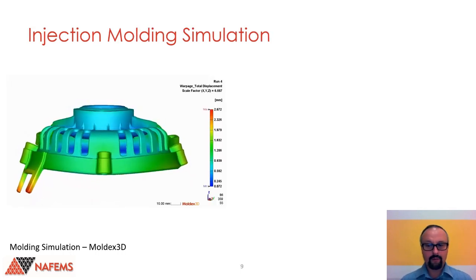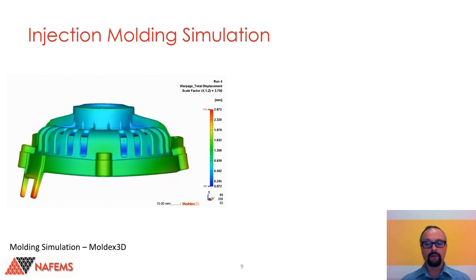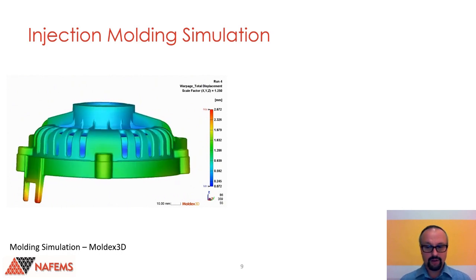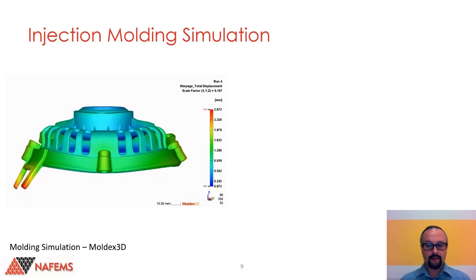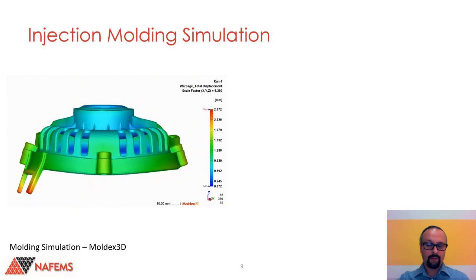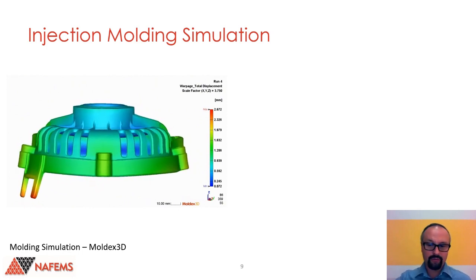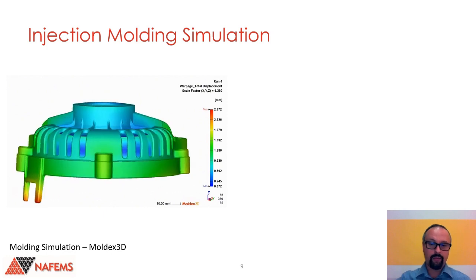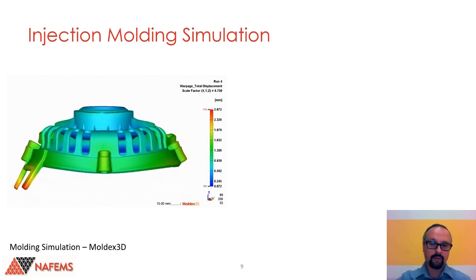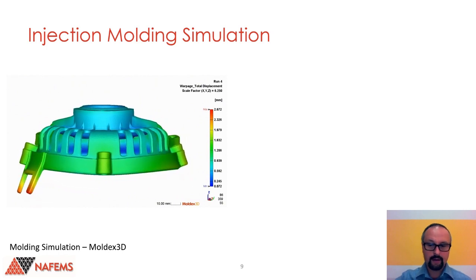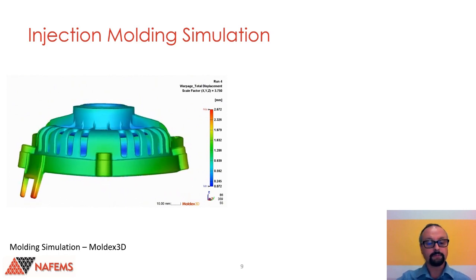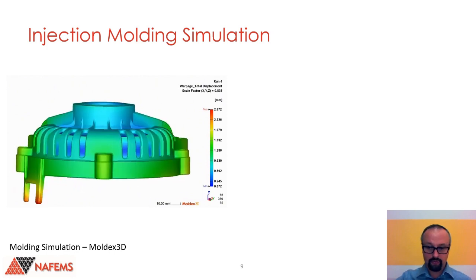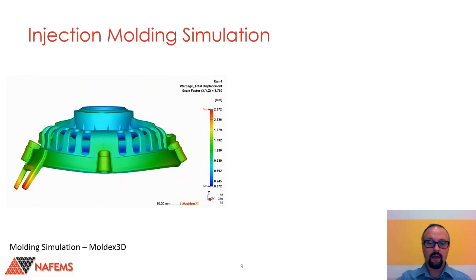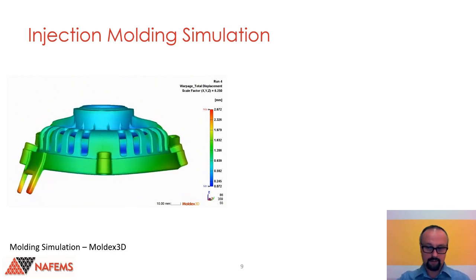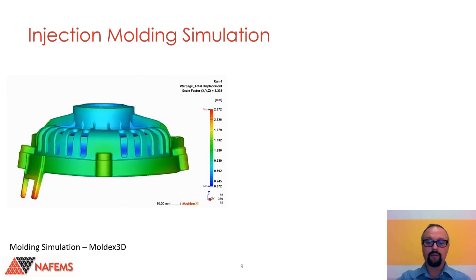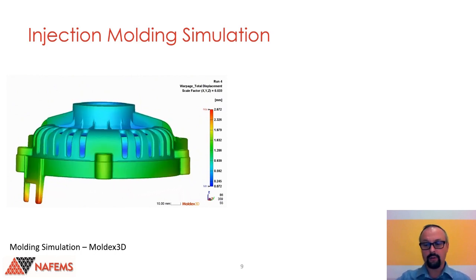Even though we design our geometry according to these DFM rules, with a constant wall thickness, we still need to double check it with this injection molding simulation, because as you can see here, it appears that our well-designed geometry has a post-molding deformation, warpage, of almost 2.6 millimeters in this specific area here. And of course, with software, with Moldex3D in this case, we can not only predict the displacement, the value of the warpage, but we can also try to avoid it by changing our geometry.